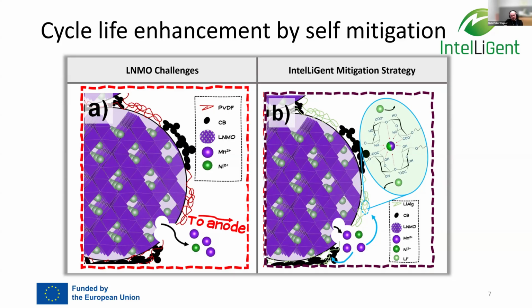So our concept involves the binder and functionalizes the binder in a way that it can interact with any divalent species dissolved into the electrolyte and trap them, and then instead release further lithium ions into the system, and hence interrupts this evil cycle.